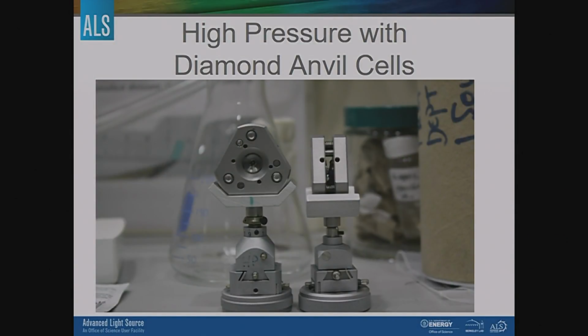Usually, for a single crystal experiment in a DAC, you want to have the greatest opening angle possible, and you also want to have about the hardest X-ray energies possible to compress reciprocal space down small enough that you get as much data past that issue. So you definitely won't get all the data. This is why high pressure people love high symmetry systems, because then it's a smaller chunk of reciprocal space they need to access. But with the opening angle and harder energies, you can get very good reciprocal space coverage. I figure if you can get 75% of reciprocal space, then you're ecstatic, generally.